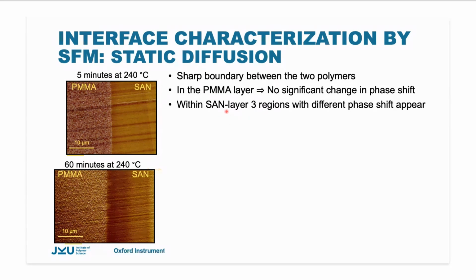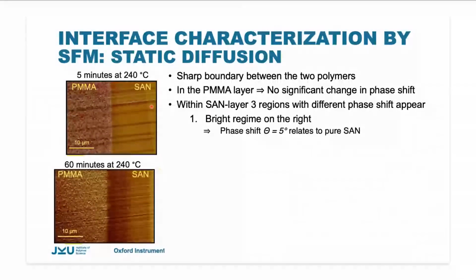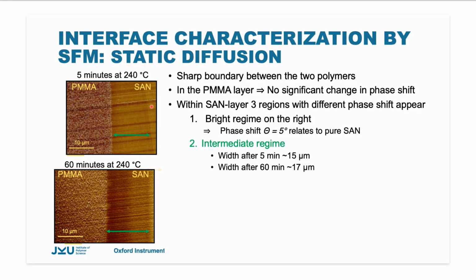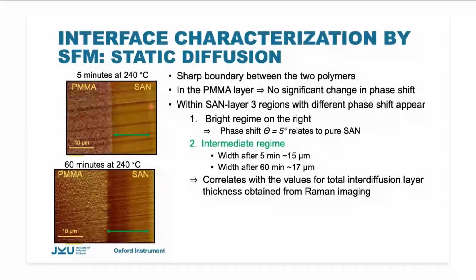layer, we could discriminate at least 3 different regions within the phase shift. First, we have a very bright regime on the right, as I show here. Here, the phase shift is about 5 degrees, which relates to the pure SAN. Then we have this intermediate regime. The width of this is between 15 and 17 microns, which correlates to the values we found for the total interdiffusion layer thickness obtained from Raman imaging. This gives a good indication that we have here the interdiffusion layer due to the intermixing of the two polymers, hopefully.